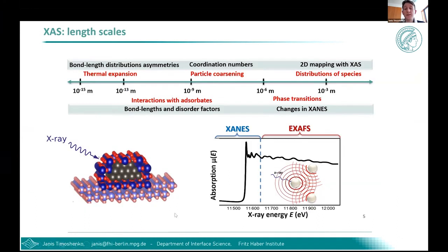So in general, we can split this X-ray absorption spectra in two parts, X-ray absorption near edge structure or XANES, and extended X-ray absorption fine structure or EXAFS. And the physics in both regions is the same, but approximations which we need to describe both these two regions are different. And also different information can be learned from XANES and EXAFS parts of absorption spectra. In particular, XANES is mostly sensitive to electronic properties, to oxidation state of the material, while EXAFS is mostly sensitive to the geometry of the material.